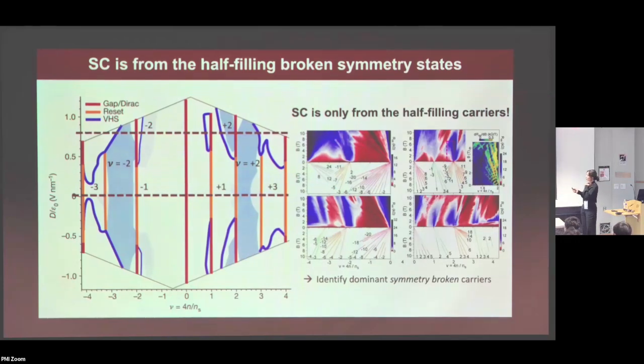Surprisingly, the result tells us that the superconductivity appears only when your charge carrier is the symmetry broken nu equal to plus or minus 2 type, the so-called half-filling carriers. Once your carrier type changes to either plus or minus 1 or 3 or something else, you don't have superconductivity. Normally, if you have just one line, which is the case of magic-angle twisted bilayer graphene, and you still obtain this kind of result, who knows, it might just be a coincidence, right? But now we have the entire y-axis dimension, and it always follows the exact same trend. Even though the superconducting dome shape changes and everything, the carrier density is still exactly what's mapped.